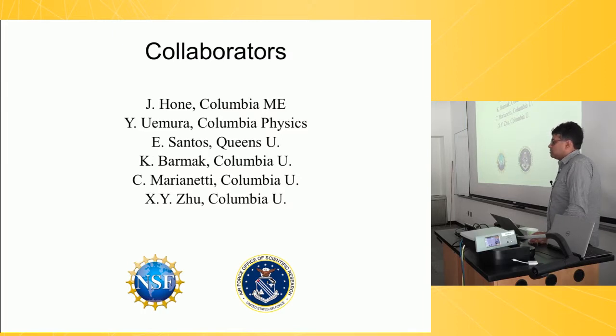Hi. So you mentioned that you saw these defects are magnetic in at least two materials, molybdenum diselenide and molybdenum ditelluride. Do you expect it to exist in most semiconducting TMDs? So we actually have beam time to measure the tungsten-based ones. So far we've seen it in all the molybdenum-based TMDs. We haven't studied the tungsten-based ones yet, and so that remains to be done.